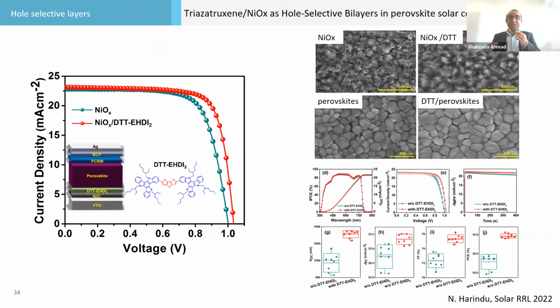And with nickel oxide, we have a very thin layer of triazatruxene, which you can say is a passivation, or a very thin bilayer of triazatruxene. We take 20 nanometers of triazatruxene and 30 nanometers of nickel oxide. So this is the nickel oxide. It was not good, so you can see there were pinholes. So we deposit some triazatruxene here. So we thought that this interface will be better.